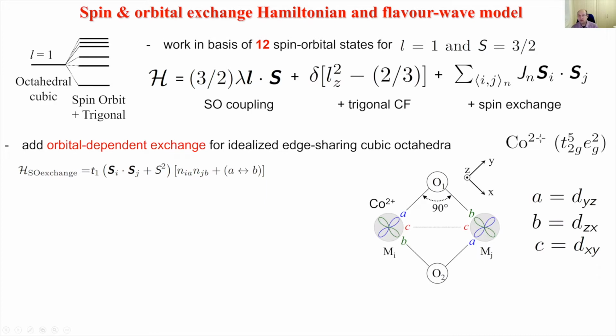So now for cobalt 2+, the unpaired electrons are in d orbitals, and they can be of the form t2g or eg, where t2g orbitals are sort of threefold orbitals like this that are confined to the XY, YZ, or ZX plane. So if we consider here an idealized geometry of cobalt-oxygen-cobalt exchange, then we have to take into account the specific orbitals through which exchange can happen. So for example, this blue colored orbital here labeled A can have an exchange via the oxygen with the green orbital labeled B here. So we can have an exchange between the A orbital and the B orbital here.